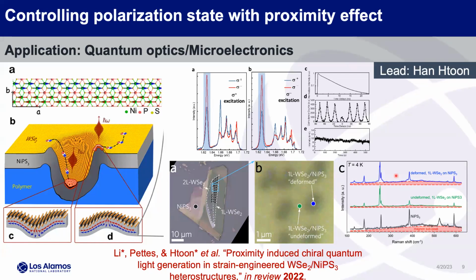So magnon intensity: if you go below the Néel temperature, you'll be able to pick up magnons, which are the collective magnetic oscillation. So much like when you're doing analytical electron microscopy and looking at plasmon peaks in EELS, you can see magnon peaks in Raman spectroscopy. And it was much stronger by at least a factor of 2, averaged over the sampling area, in the areas where we did the punches.